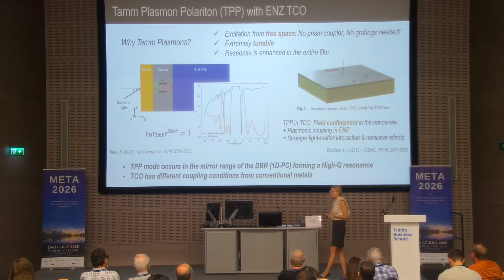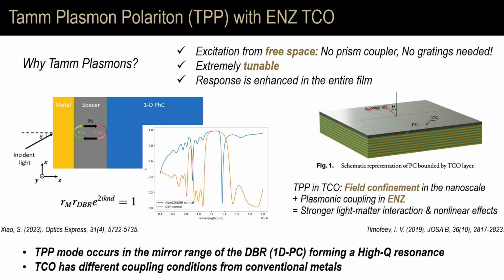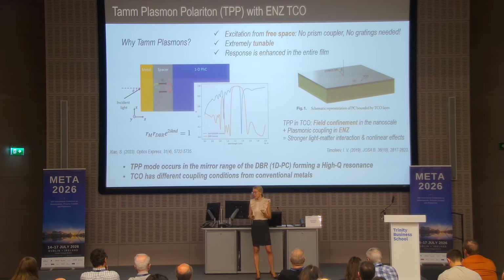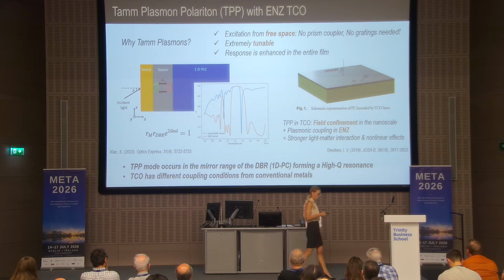So in order to do this and achieve this high electron temperature, again, you have to confine light in the transparent layer, which is very, very thin. So for that, you can use different concepts. Again, I'm combining material and the design here together. And this concept is a concept of Tamm plasmon polaritons, where we actually got an idea from the work by Timofeev, where you have basically a Bragg grating and an extremely thin layer of TCO on top.